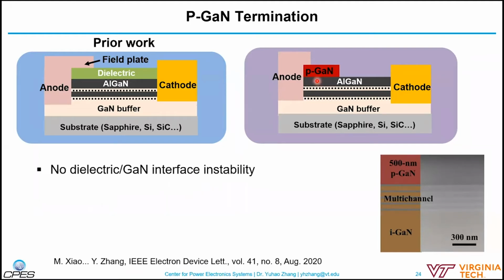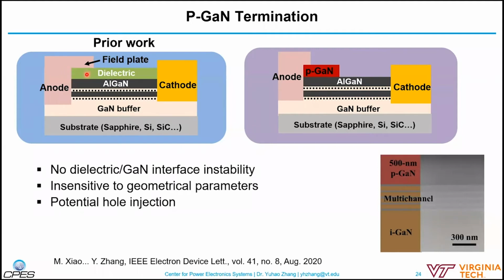There were a couple of benefits, and the first one, it doesn't have a dielectric and GaN interface, so many of the instability issues can be avoided. Also it's not very sensitive to the geometry designs, for example, the dielectric thickness, field plate length, etc. And potentially it can allow hole injection, which can make the device sustain very high surge current, etc. And also, it's compatible with the P-gate HEMT process, which is in all of today's gallium nitride foundries.